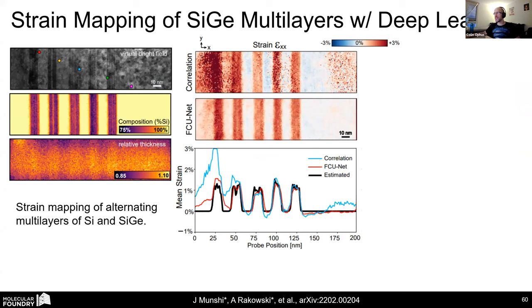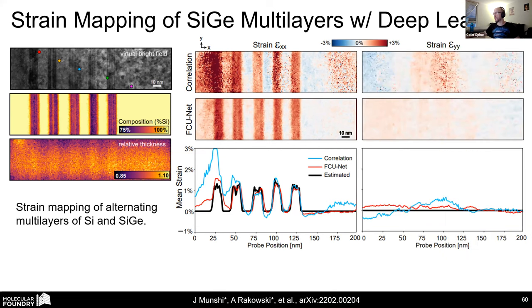So this is the EELS, electron energy loss spectroscopy, of this material. Once we know the precise germanium content, we can use Vegard's law to solve for the local lattice strain. And that's what I've colored in black here. And if you compare the correlation to the FCU net complex measurement here, it's like night and day. The correlation method is affected by tilt of the sample, it's affected by surface oxide, it's affected by noise, it has all these systematic errors. And in the other direction, the epitaxial direction, it's equally bad.